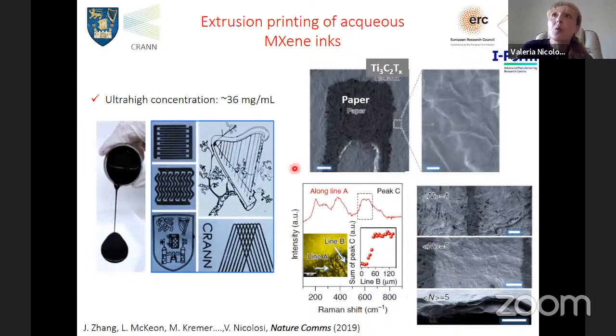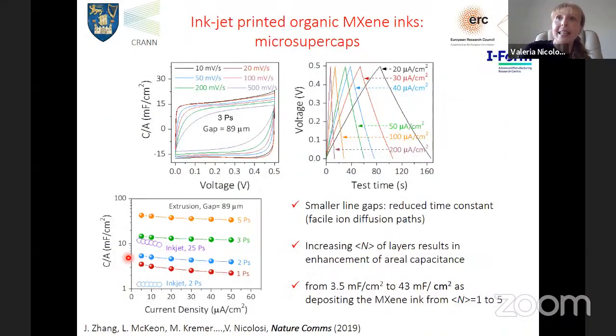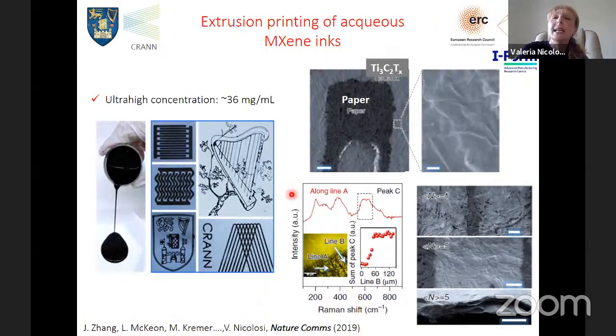This was indeed also what we managed to print out of extrusion printing. This was very, very good because with extrusion printing, you can simply print water-based inks, not organic solvents like in this case for inkjet printing. And we could really print any sort of device with any shape. Open your imagination, you can start printing these devices with any geometrical shape that you like. Again, printing on paper, PET, whatever substrate you like. And again, you can see how nicely the ink is printing.